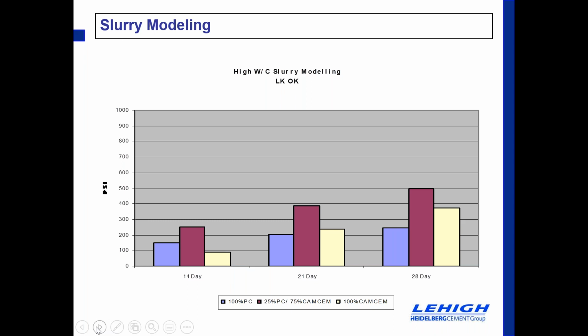You can see that in most cases we were doubling the straight cement strength. And in these applications, you know, this is not ready mix concrete. Typically we're looking at between 300 and 600 as the target strengths. It can vary up to 1,000 on some geo jobs, but typically that's the range. So in this application, we probably could have used 100% slag to achieve something that would have been acceptable, in this case, better than Portland cement. But that is also because of the other mixtures that was going on in the soil and so forth. Next, please.